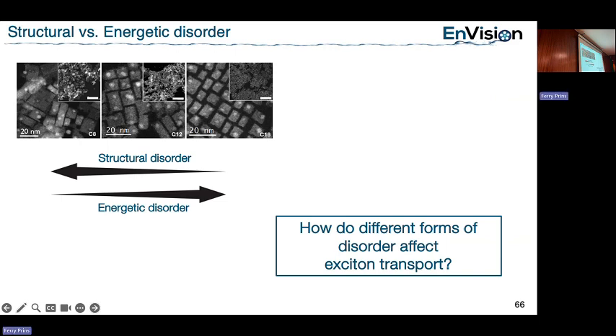And that effect, making the transfer rates asymmetric, is what results in your subdiffusive behavior. Whereas for the other one, you really need to probe a very large area, and we know we're not moving very far—80 nanometers at best. So you're not making many hops. You have something that lives very long, and if you can probe the entire structurally disordered thing, then you can start seeing some diffusion. But that's on a very different time scale, a very different length scale.